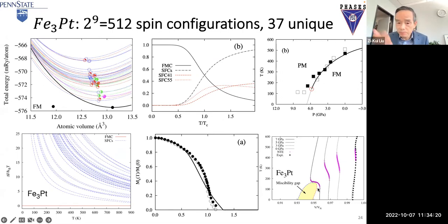So again, this is really predicted with DFT calculations, putting in some statistical mechanics, and predicting this transition. The only thing we have to assume is that when the transition takes place, 50% is a good criterion. You can also use heat capacity or magnetization and other quantities to compare, but we found this one is the most robust comparison.